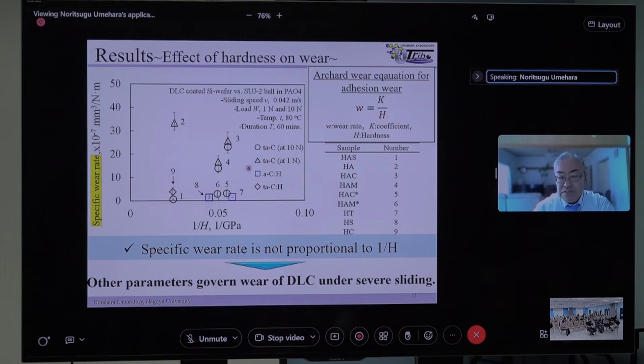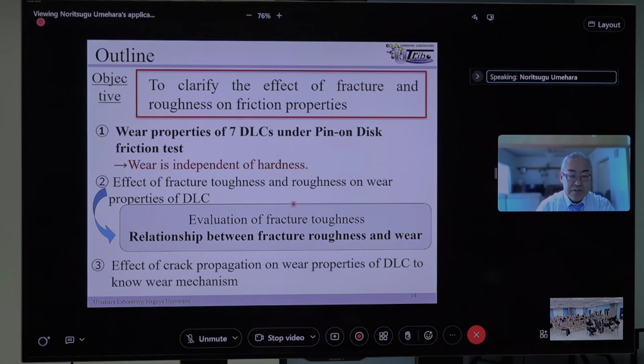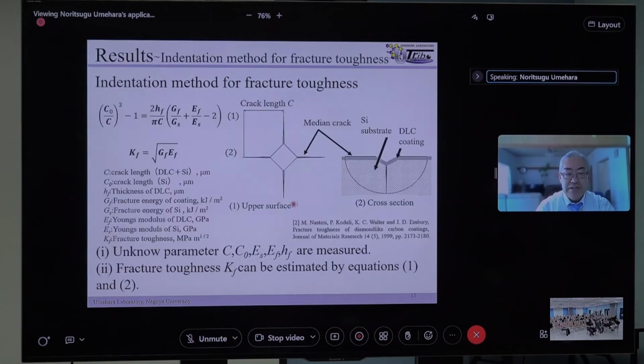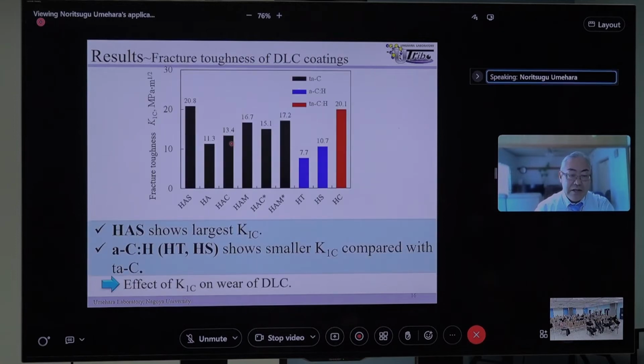But from this result, you can see the specific wear rate cannot be well understood by hardness. So it means we need other parameters. Maybe other parameters govern the wear of DLC under severe sliding. So we have measured the fracture toughness using the Nastasi way, from this equation. Finally, we can get the fracture toughness of each one.